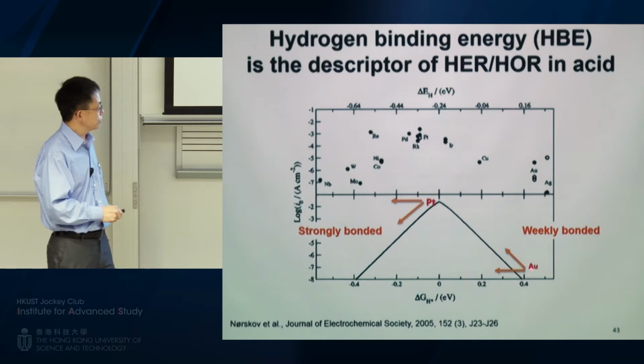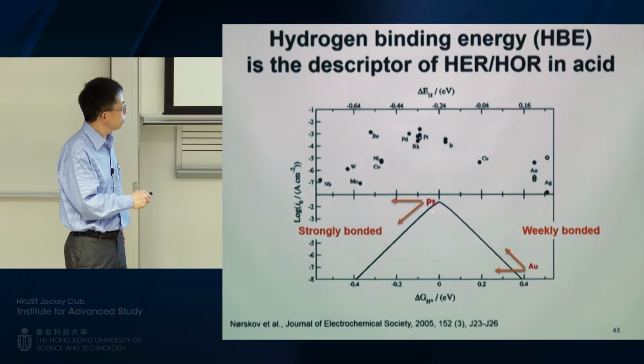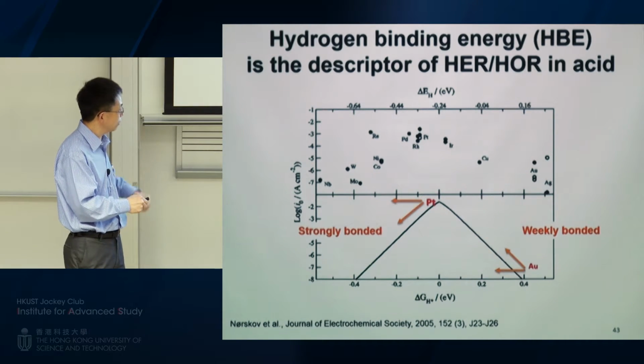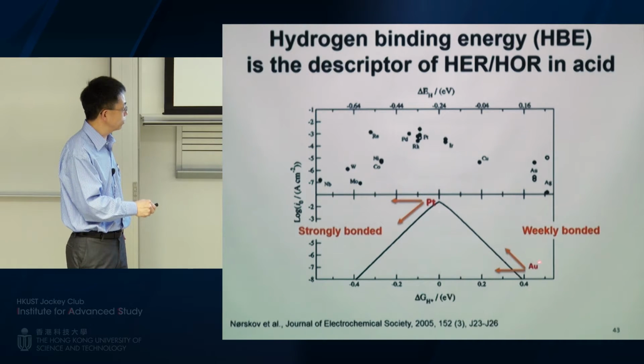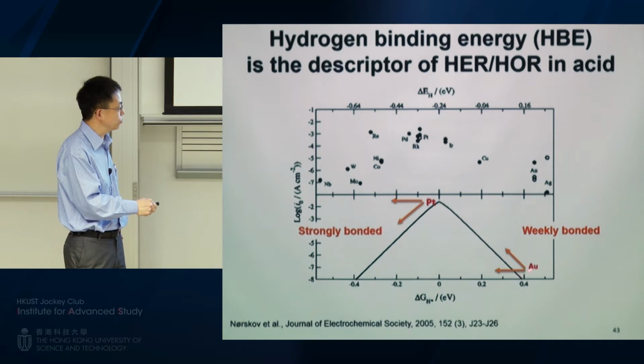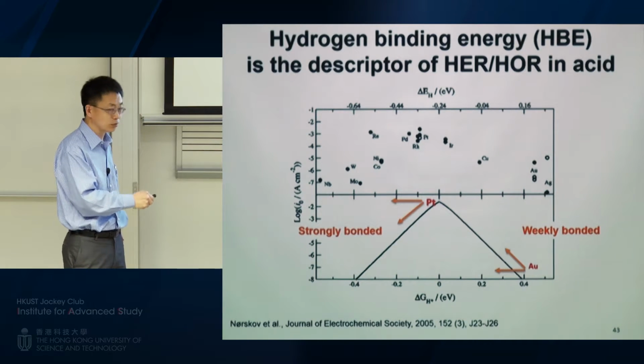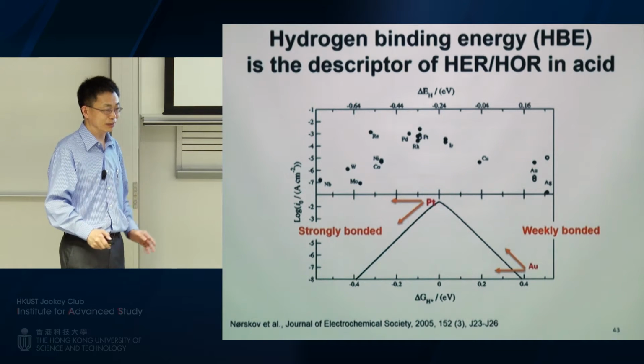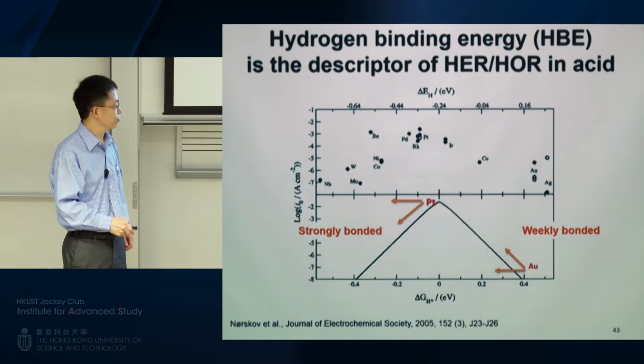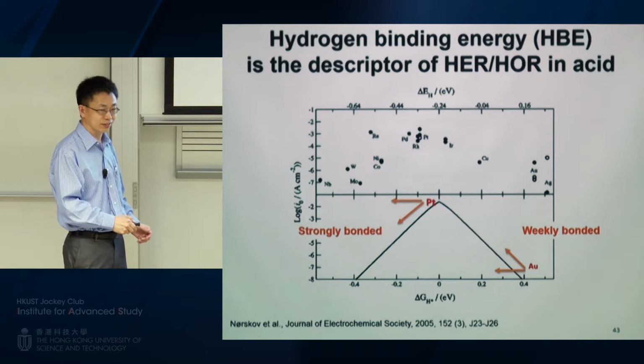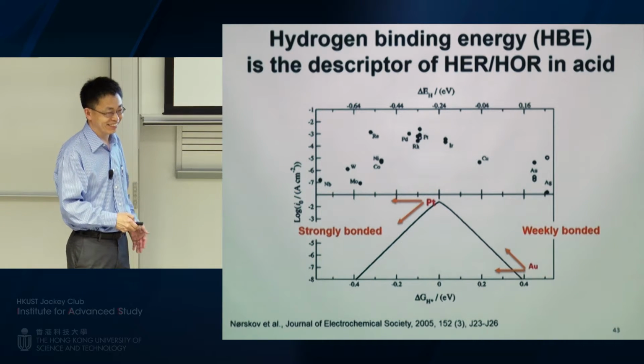What was interesting is, immediately we started thinking, wow, if you have platinum sitting here, you move from acid to base, and your binding energy getting stronger and stronger, the activity is going to get lower and lower. We saw that. What about gold? Gold is hanging out here with a very weak hydrogen adsorption. If we started scanning from acid to base, maybe this one will climb up, right? So I had a PhD student who started saying, let's try it. And so far he's been telling me, no, it's still going down. So it didn't go up. So we need to figure it out now.